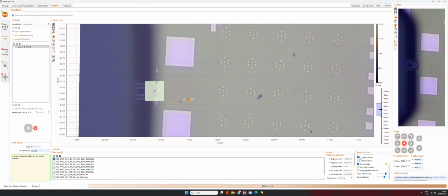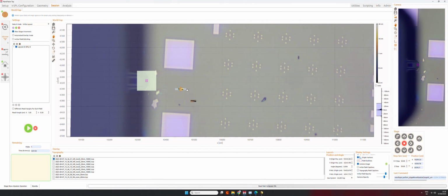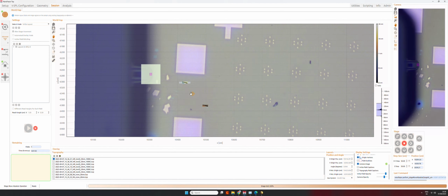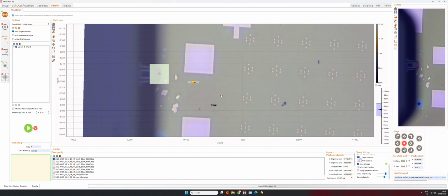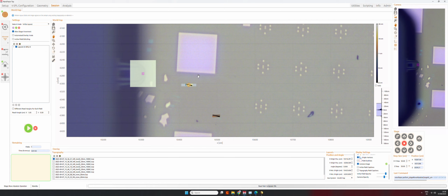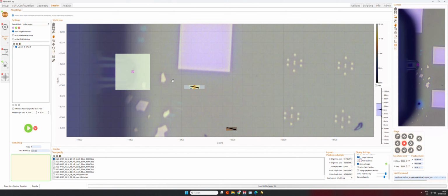First of all, which kind of samples do we have? We have what we call a training sample. Some of our NanoFrazor users should have this sample. It's a sample with the silicon substrate. We evaporated these structures. The structures are made of chromium and they're about 30 nanometers in height. So it's a sample that can be used for training, indeed.